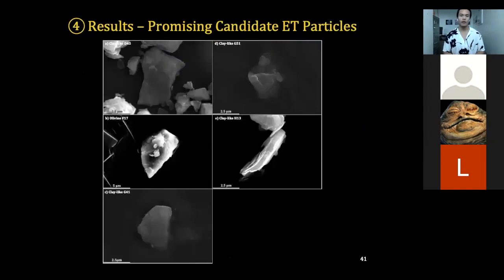Moving on to some of the promising ET particles that we ended up choosing. We chose 5 of them. Again, these ones have compositions that fall within a stricter factor of 2 times to 3 times the CI chondrite composition. Images A, C, D, and E all have a clay-like texture and composition, and image B has a texture and composition that is similar to an olivine.